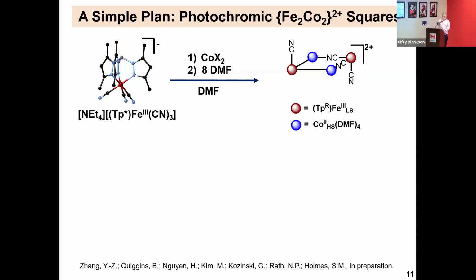You'll notice that when you self-assemble these in a variety of solvents or capping ligands, you get these molecular squares where you have 2 cyanides bridging between the iron and the cobalt, and you have a terminal cyanide poking out into the outside world. And they're always anti, or oppositely aligned with respect to each other, and that's to minimize the dipole moment.